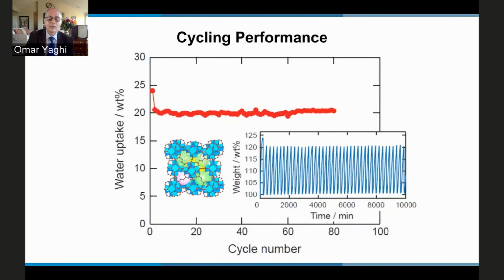But before, we wanted to show that, in fact, the water can go in and out with great facility. And so at the time, we did around 80 cycles with absolutely no imprint left on the MOF, and the MOF is stable. Except we saw that after the first cycle, there's a drop in capacity. And so we wanted to know what's going on.